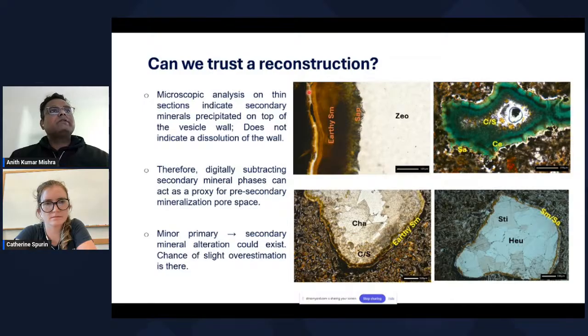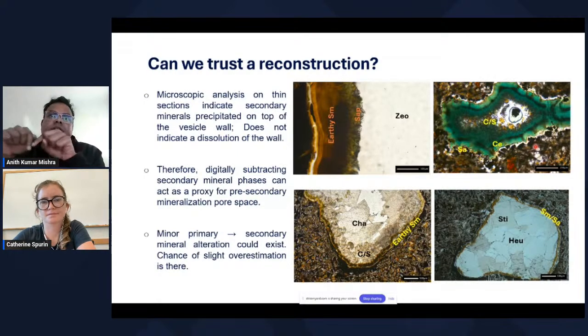The secondary minerals have precipitated directly on top of the vesicular basalt wall. The same thing we can see in here. So this is the primary basalt matrix. Here we have the first layer of smectite, then we have chlorites, then we have chabazite, which is a type of zeolite. The same we see in here, the same we see in here. So the idea that we got from here is that the secondary mineralization within the vesicles has not altered the pre-mineralization vesicle shape or vesicle size. It precipitated directly on top of it without altering the boundary.